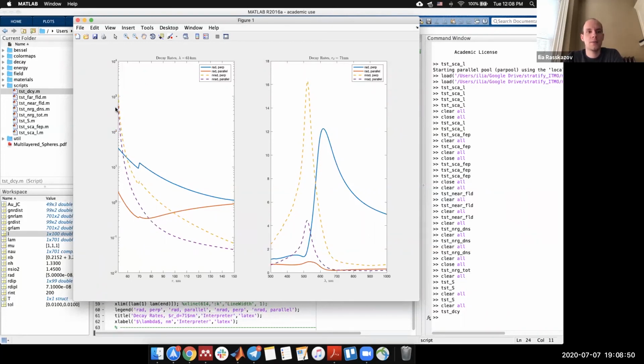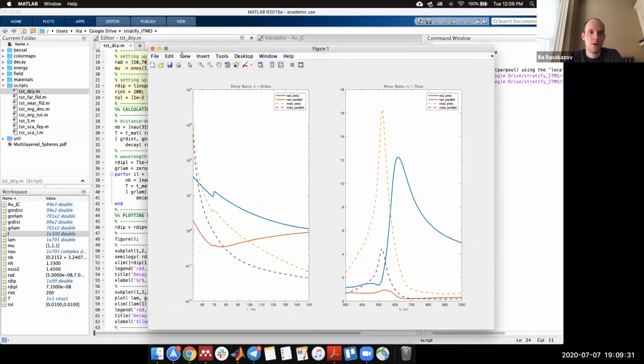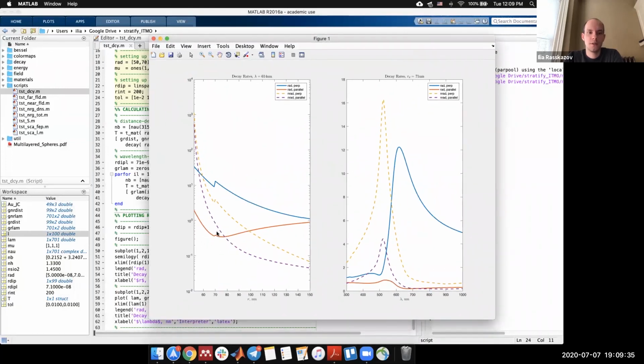And the reason why is because all of the radiation from the dipole goes inside the sphere. Essentially, that's why in all of the fluorescence experiments, in all of the upconversion experiments, you need to separate the dipole emitter and the surface of the metallic core by some dielectric spacer. So look here, if you put the emitter on top of the dielectric, whose boundary is located, let me double check, at 70, so our outer shell is 70, that is the boundary of the dielectric outer shell.